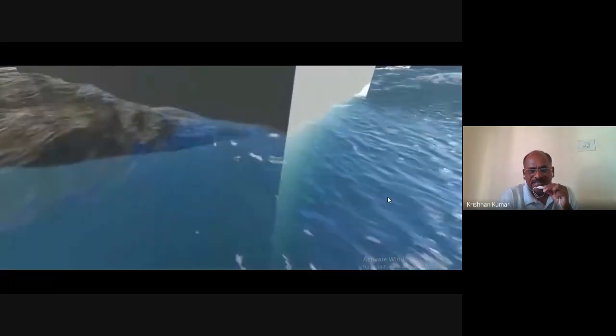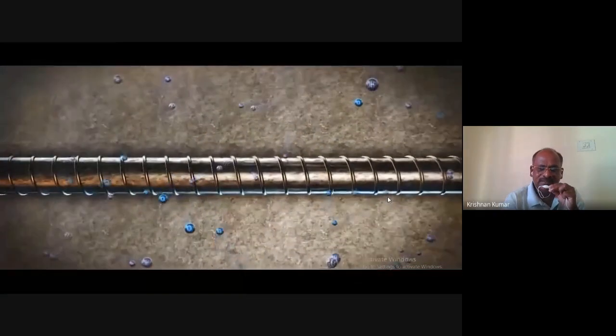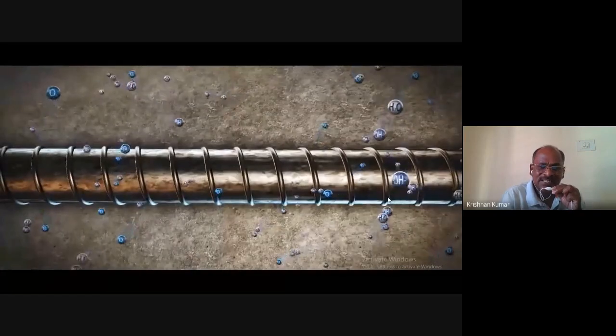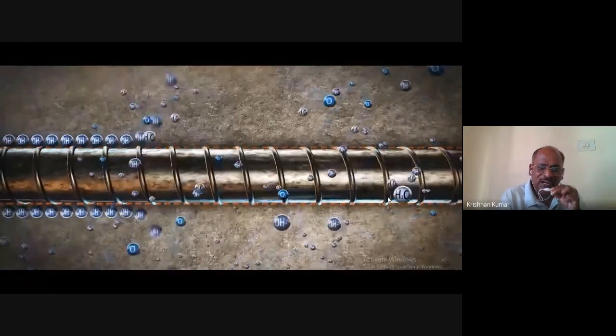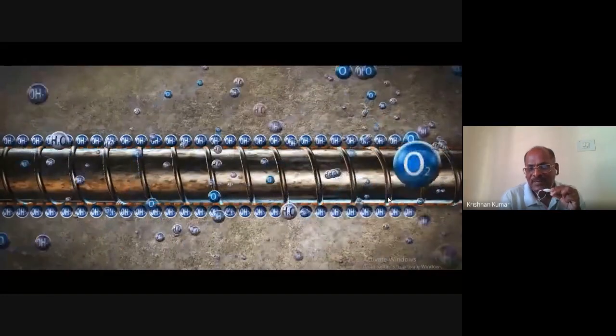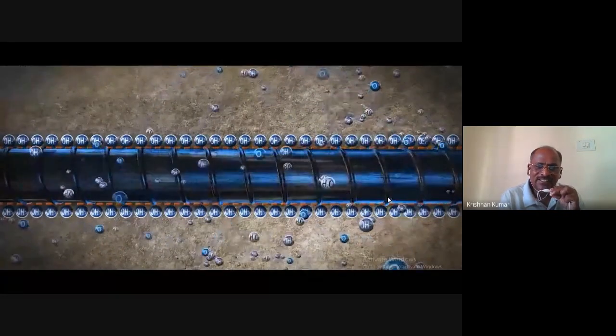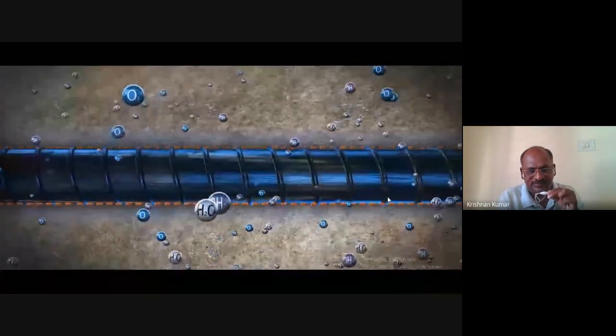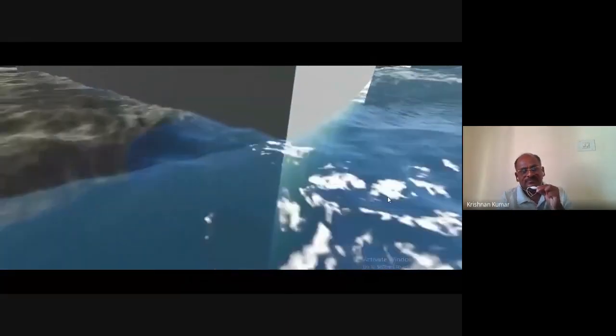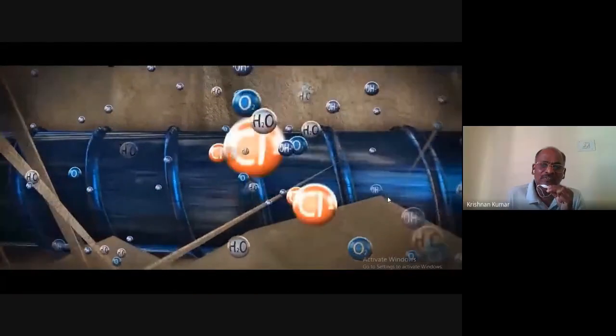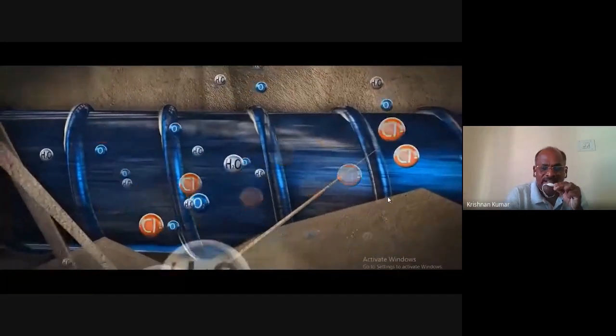So this is the new structure when you are constructing, without any effect of this. Now these are the oxygen, Ca(OH)2, all these together form a passive film. The formation of the passive film over there is the protective oxide layer. As long as it is there, there is no problem. When the chloride comes in, the chloride tends to move nearer and attach to the steel reinforcement because of Fe2+.